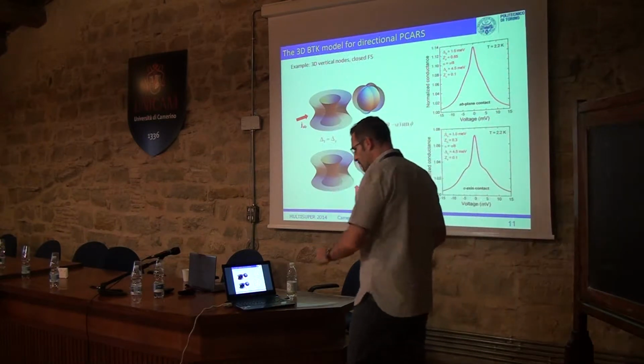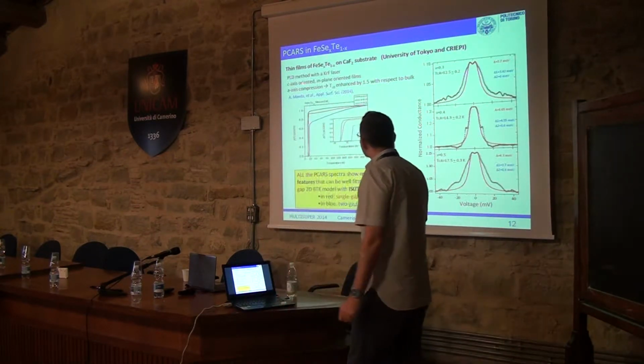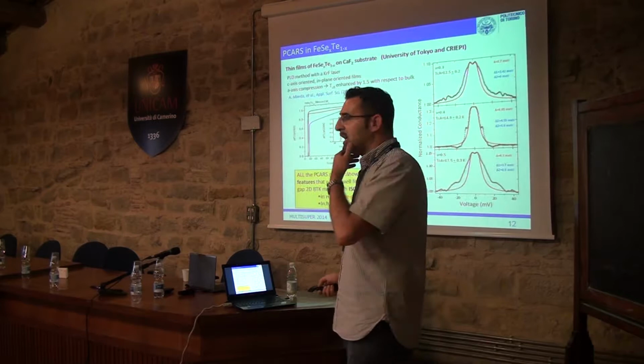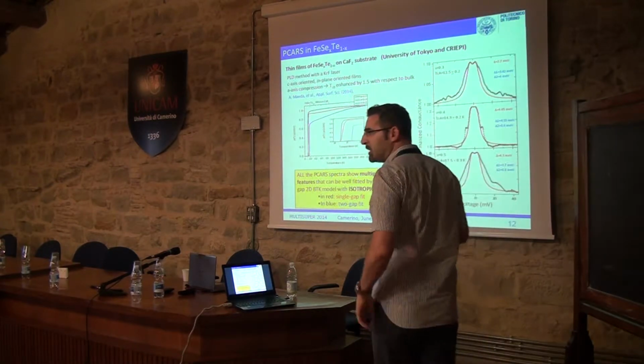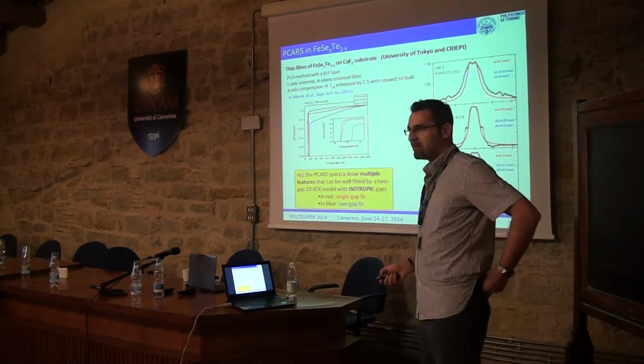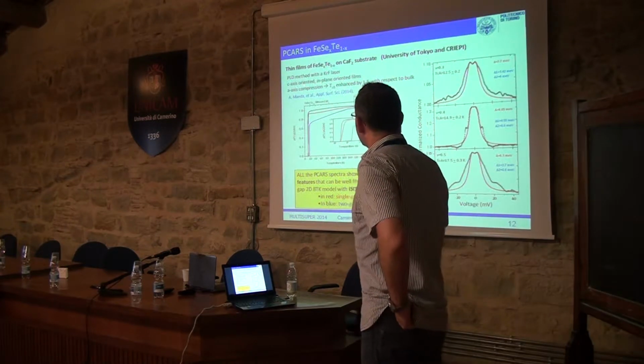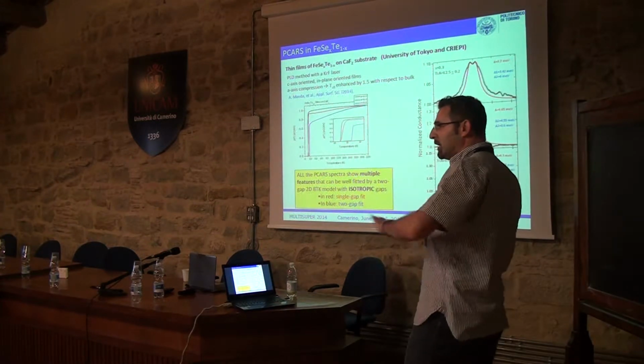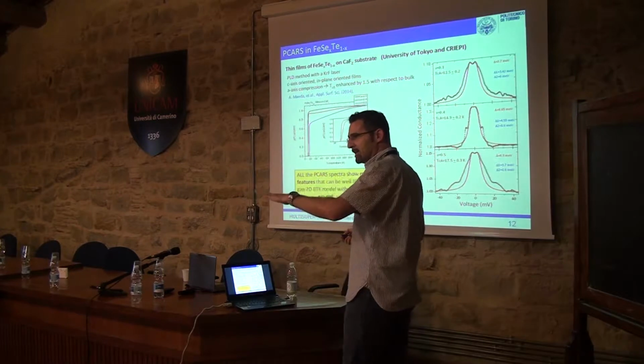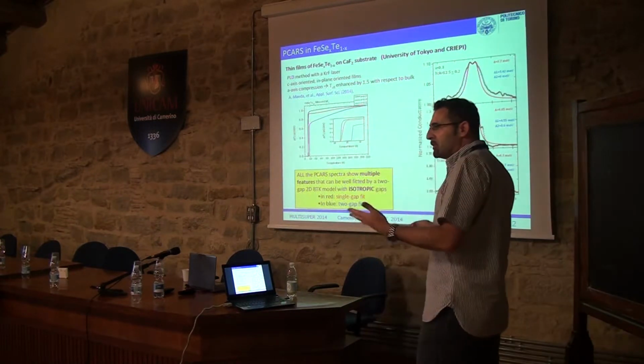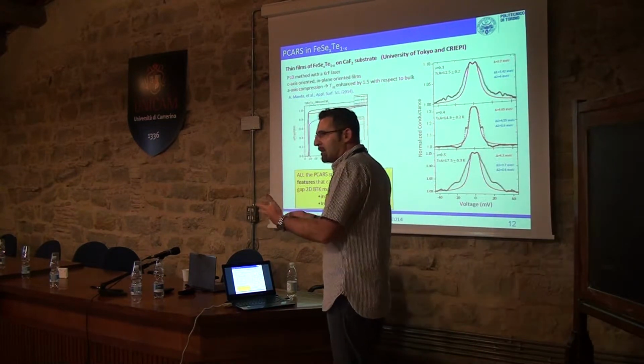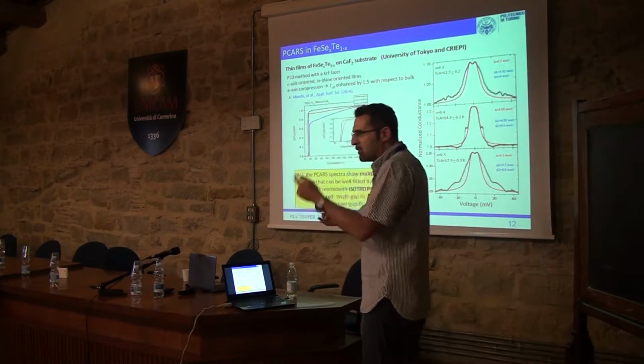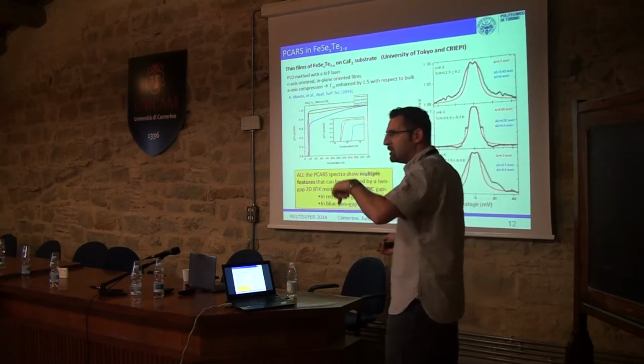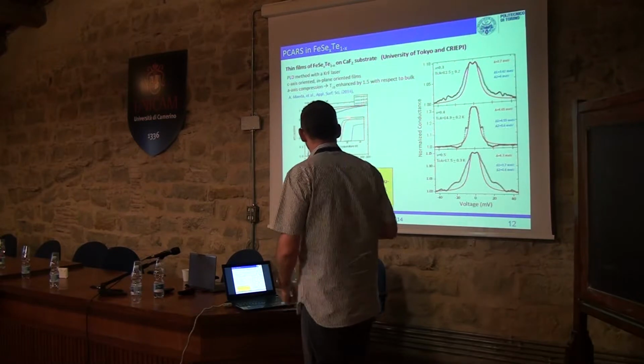Keep this in mind for the following. These are point contact spectroscopy measurements in iron, selenium, and tellurium films. These films have been grown on calcium fluoride substrate in Tokyo by the PLD method. They are very well oriented along the c-axis and in the plane. So from the point of view of spectroscopy, they look like single crystalline junctions. So we perfectly know the direction of the current injection with respect to the crystallographic axis.